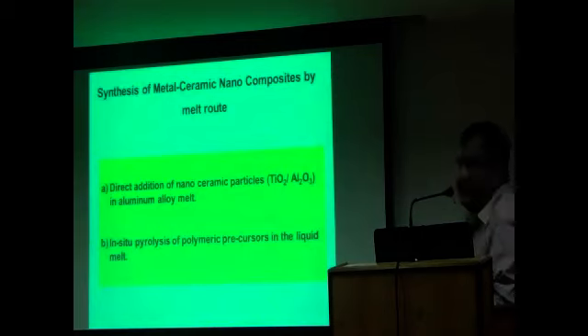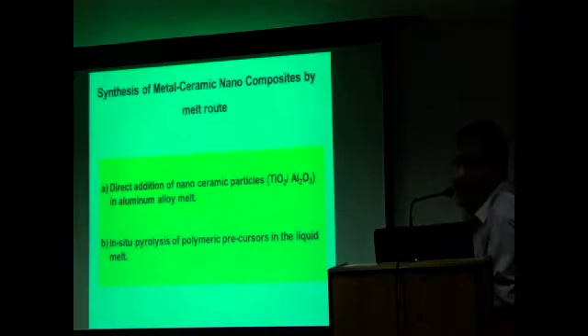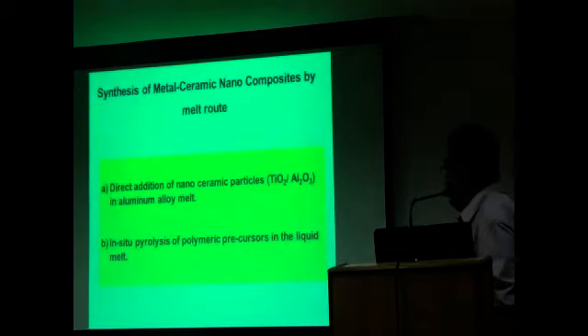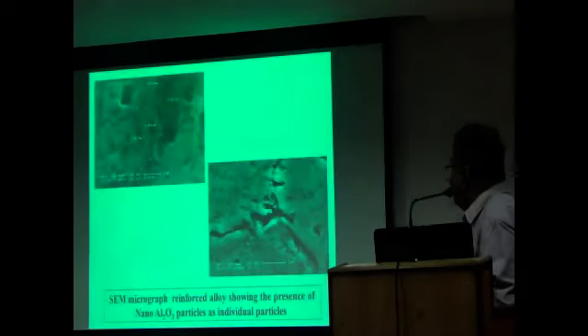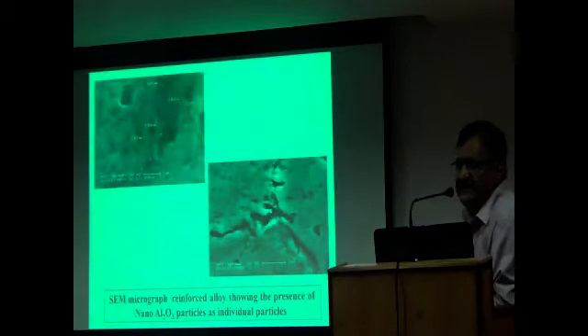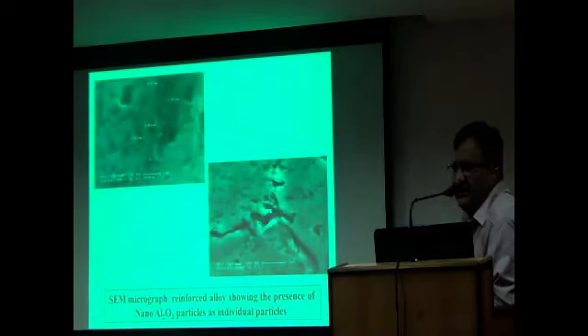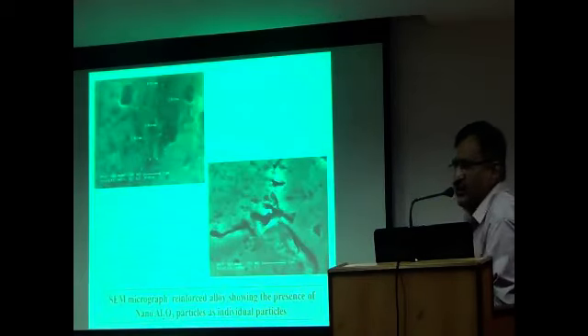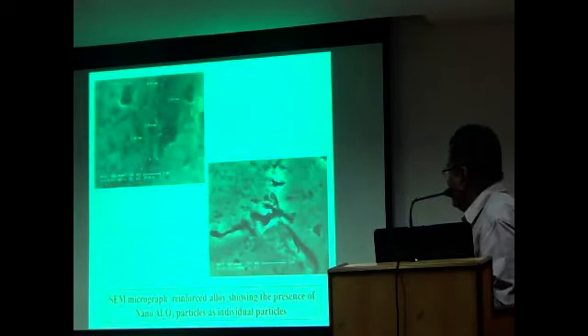So we have done this work by direct additions as well as by the in situ pyrolysis of polymer precursors in the liquid aluminum alloys. Okay, this is the direct addition of alumina particles. We have created certain specific methods to add these particles. I won't even get into that one. Okay, so this is how it looks.